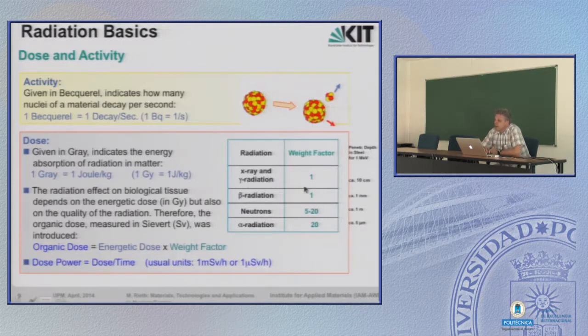You see it here. X-ray and gamma ray has weight factor 1, as well as electron radiation or positron radiation. Neutrons have a much higher impact on the organic damage. So therefore, the weight is between 5 and 20. And also helium nuclei, alpha radiation, has a weight factor of 20. This leads finally to the organic dose, that's the energetic dose weighted by the factor.